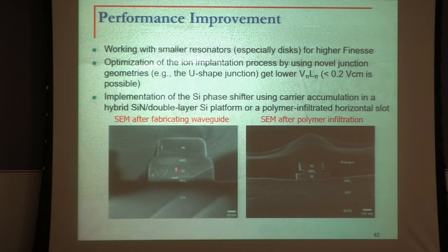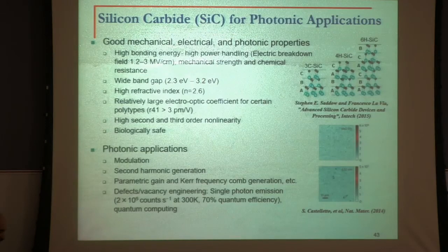I guess there is just one thought in here that we have looked into. One idea is if we can etch silicon oxide in this platform and fill it up with electro-optic polymer, then I can have a slot resonator or a slot structure, and then have a very power efficient, high speed system, because the electro-optic effect is very fast, and electro-optic modulators in slots with 100 gigabit per second have been demonstrated. These are at the infancy yet, so we have to develop the process for them.